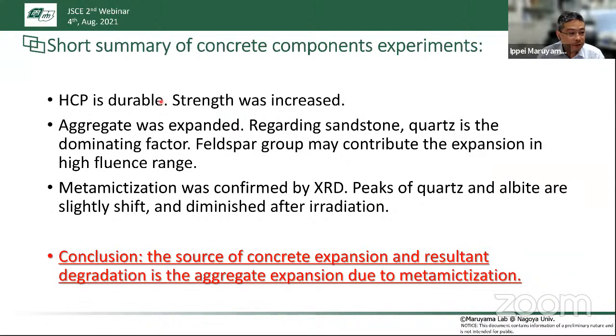And strength was increased, but the aggregate was expanded. So regarding the sandstone, quartz is the dominating factor. So feldspar group may contribute to the expansion at higher fluence level. So metamictization was confirmed. So neutron destructs the crystal structure of the alpha quartz and feldspar. So the conclusion is that the source of the concrete expansion and the resultant degradation is due to the metamictization.